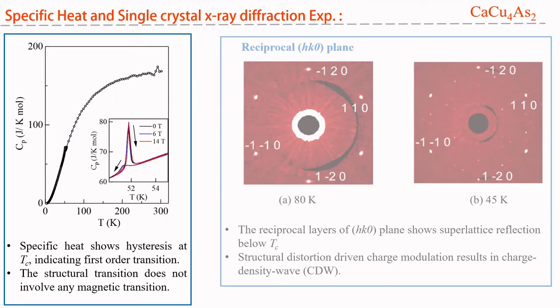The temperature dependent specific heat data shows a sharp peak at 52 K and hysteresis at the transition temperature. In presence of magnetic field, the peak value and the position do not change. This suggests the transition does not involve any magnetic transition.